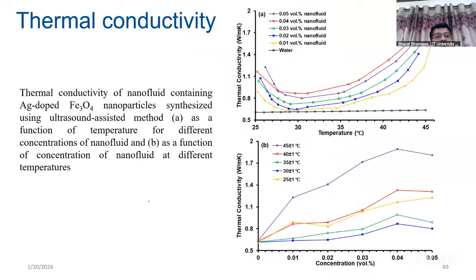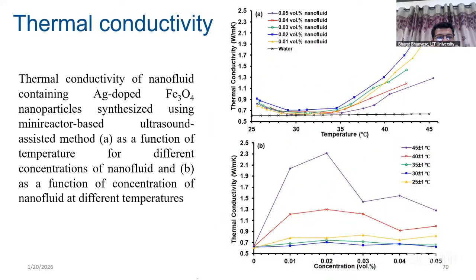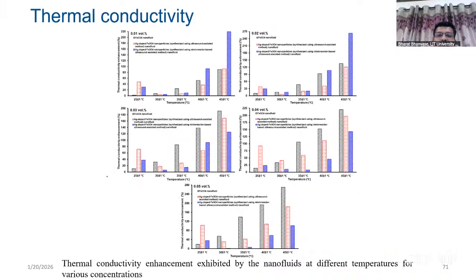In the case of Ag-doped material, an interesting phenomenon was observed. When measuring thermal conductivity at lower temperature, we observe higher thermal conductivity, and with increasing temperature it decreases first and then increases. This was the observation for Ag-doped Fe3O4 nanoparticles prepared by ultrasound assisted method or in a microreactor, with the same trend in both cases. The thermal conductivity is highest at 45 degrees Celsius, and with increasing volume percent of nanoparticles, thermal conductivity gets improved.